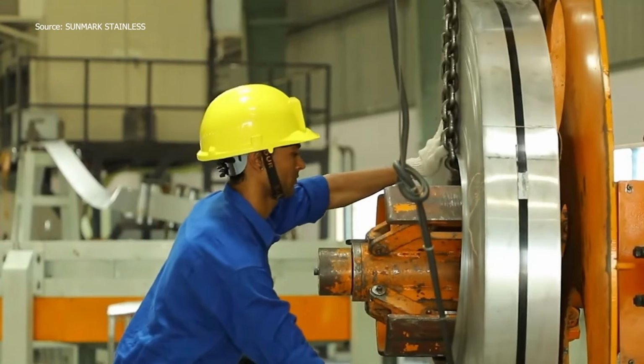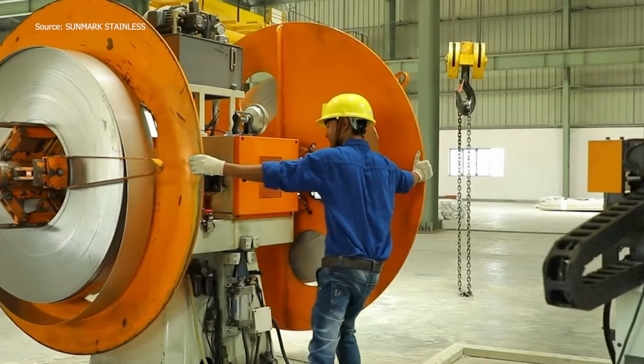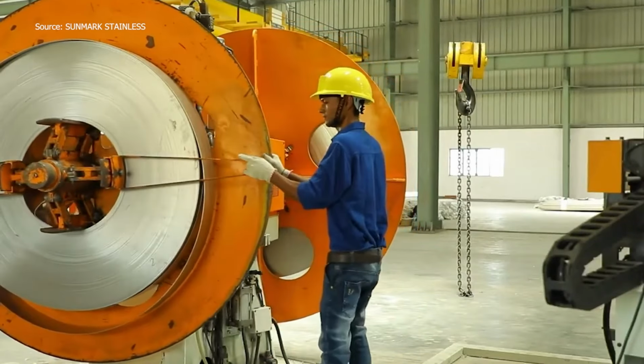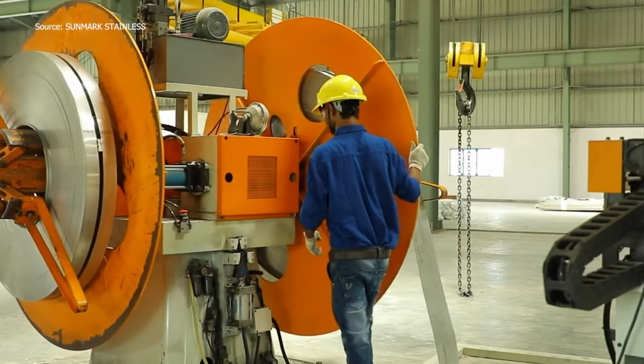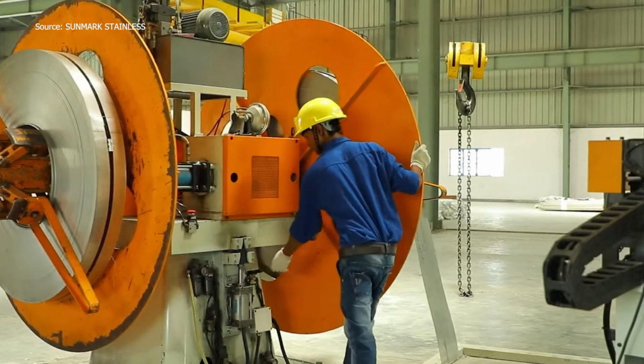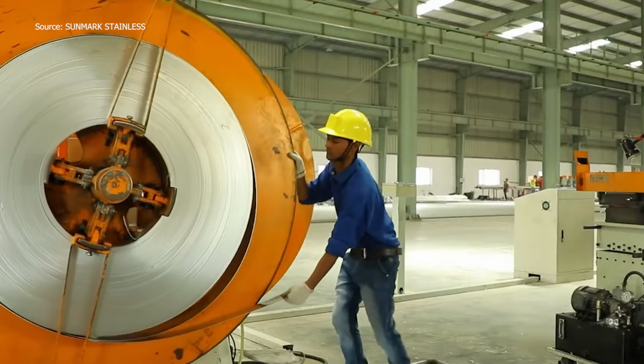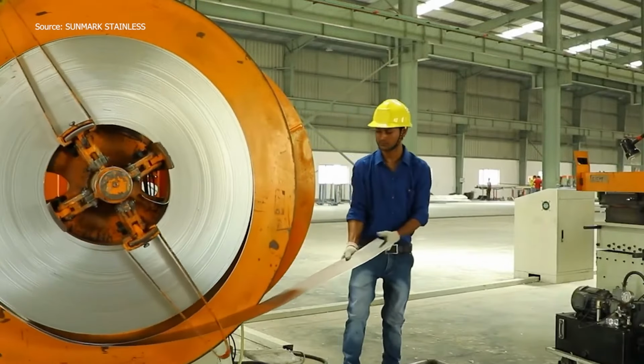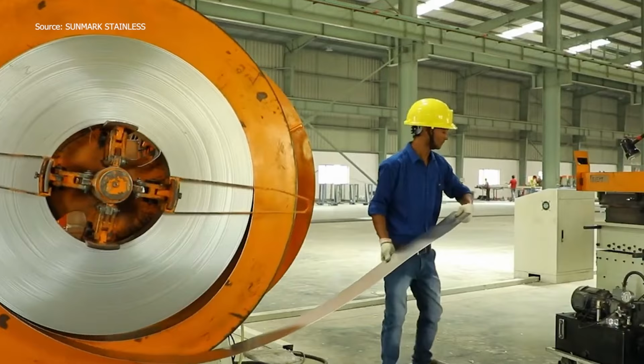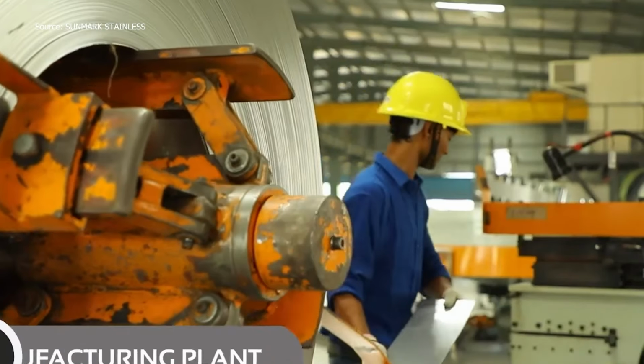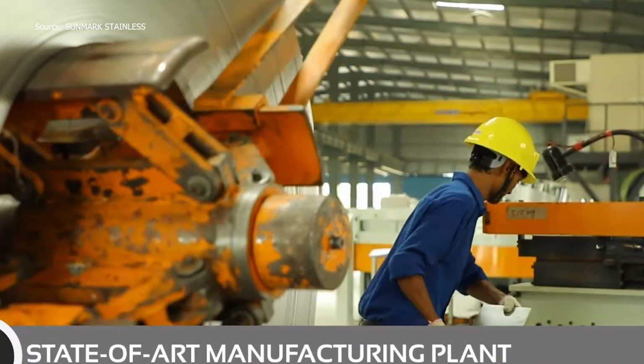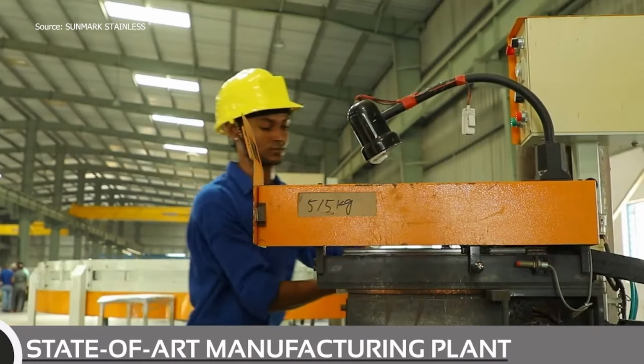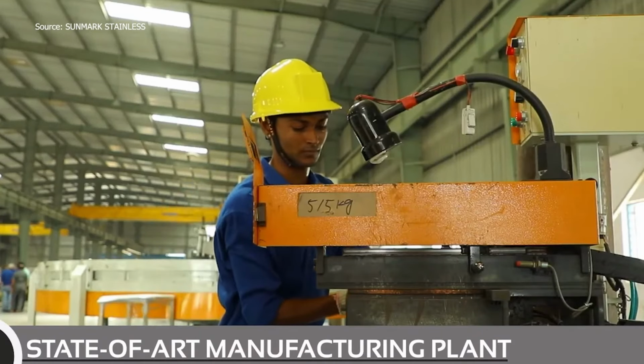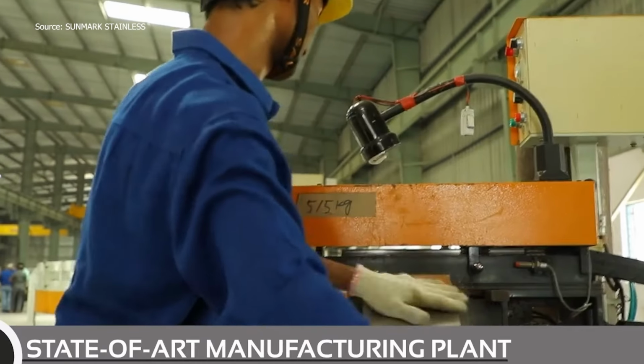Production begins as stainless steel coils are uncoiled and leveled, setting the base for tube formation. Each strip is slit to the required width using high-speed slitting machines before being fed into one of 9 advanced forming mills. The rollers gradually curve the flat strip into a perfect circular shape. High-frequency induction welding then fuses the edges with controlled energy, forming a strong, continuous joint without filler material. This seamless fusion defines not just durability, but technical brilliance born of mastery.